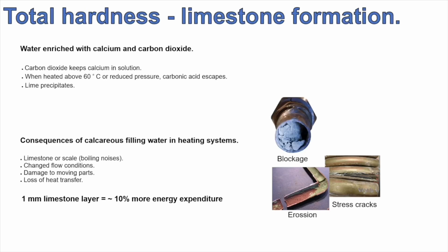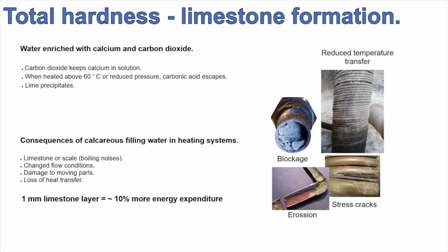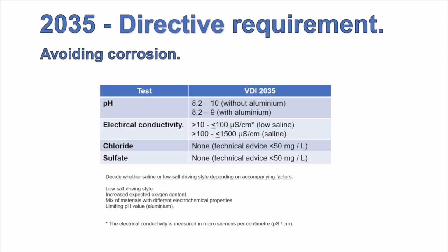1 millimetre of limestone layer can equal around 10% more energy expenditure. We've got some blockages here, erosion and stress fractures also shown. The 2035 directive is very simple to follow. This table here shows what we're looking for in terms of pH, electrical conductivity, chloride and sulfates within our system. If we achieve these, we will create an environment where corrosion cannot take place.